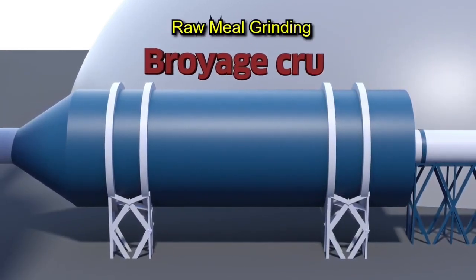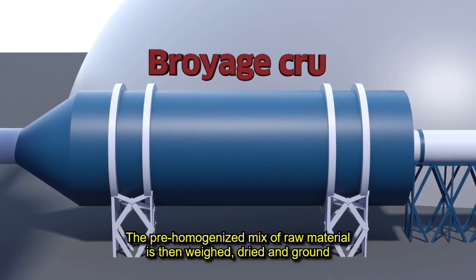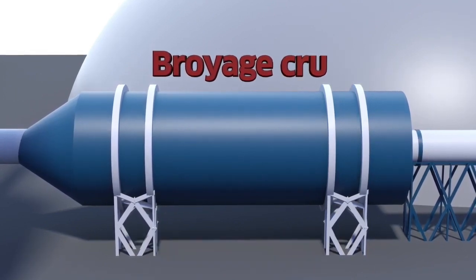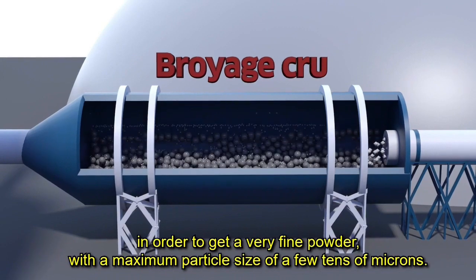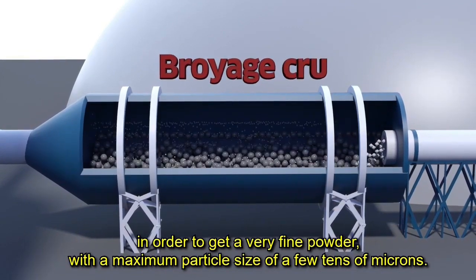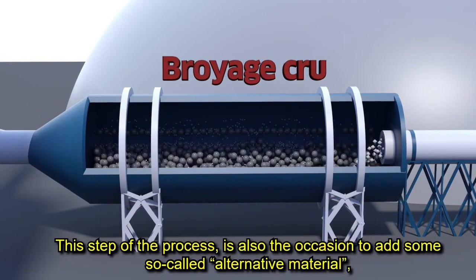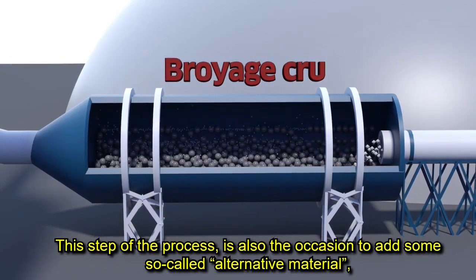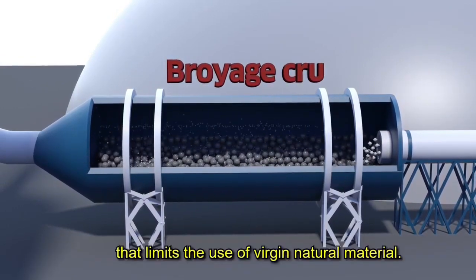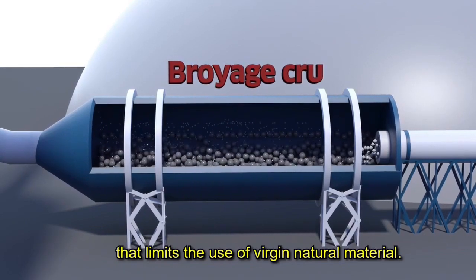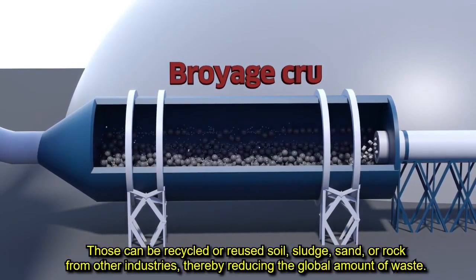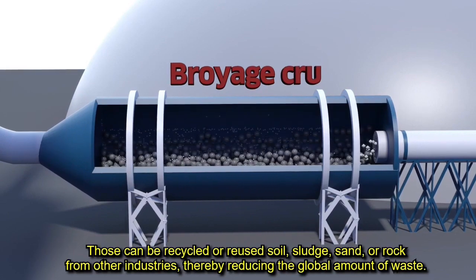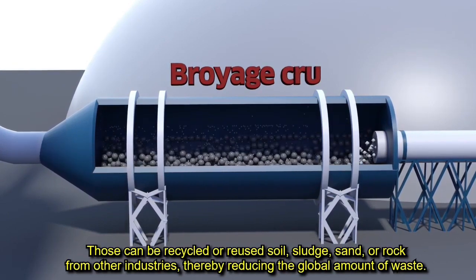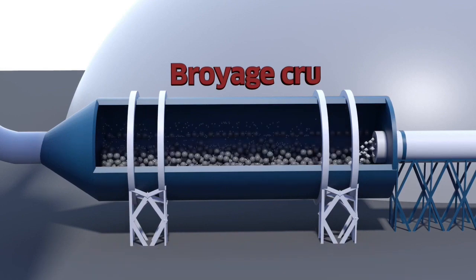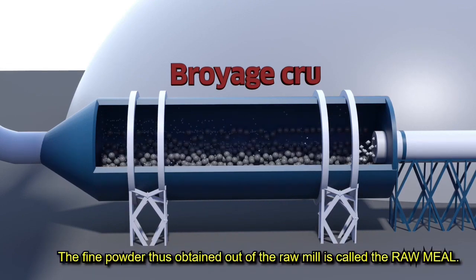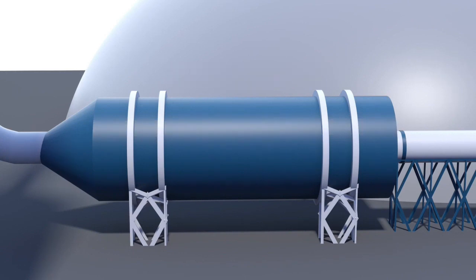Raw meal grinding. The pre-homogenized mix of raw material is then weighed, dried and ground in order to get a very fine powder with a maximum particle size of a few tens of microns. This step of the process is also the occasion to add some so-called alternative material that limits the use of virgin natural material. Those can be recycled or reused soil, sludge, sands or rocks from other industries, thereby reducing the global amount of waste. The fine powder thus obtained out of the raw material is called the raw meal.